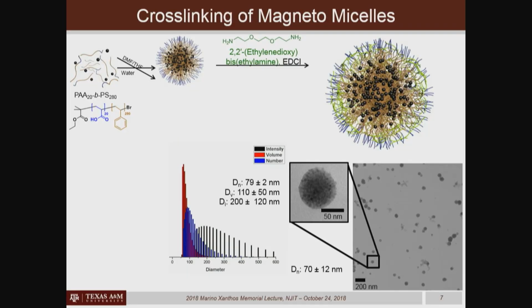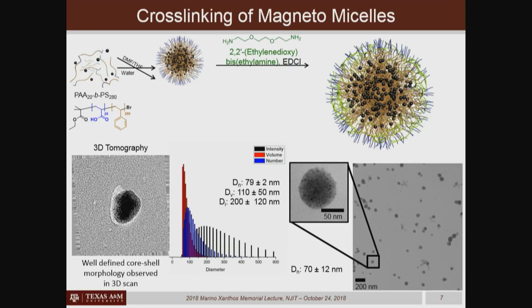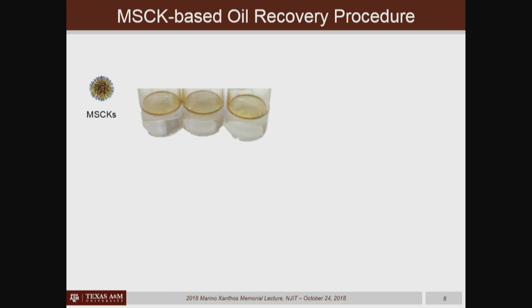Now, this told us that there was a combination of polymers and particles, but we didn't know whether the inorganic particles were on the outside of the micellar assembly, on the inside, or a combination of both. And that then was revealed by doing cryogenic tomography imaging. And you can see in this reconstructed image that the inorganic particles are in fact embedded within the organic polymer framework, as is illustrated in the upper right in the schematic representation. So these particles, in terms of their hydrodynamic diameter, are about 80 nanometers in diameter in terms of the number average hydrodynamic diameter as measured by dynamic light scattering. In the dry state, they're about 70 nanometers in diameter. So they're quite small, uniform particles.